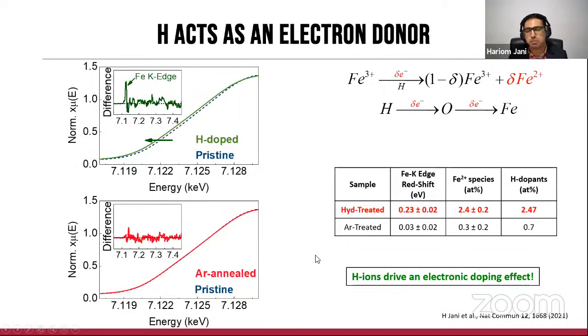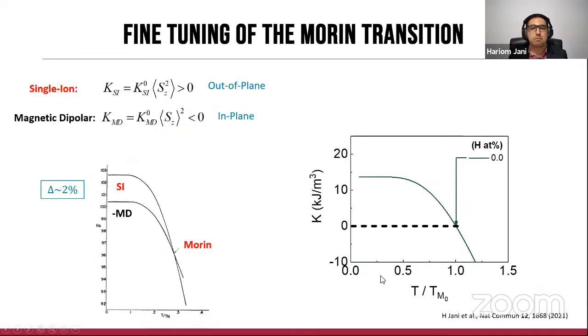And when we perform these experiments in control environments in the absence of hydrogen, any of these shifts are completely absent. So the key point here is that although we are using ions to drive the changes, it is really an electronic effect which is driving this process, which is very exciting for controlling and tuning this process. So because of the delicate coupling between the charge and the spin or the parameters, we are able to drive this transition. And this fundamentally comes because of the following argument.